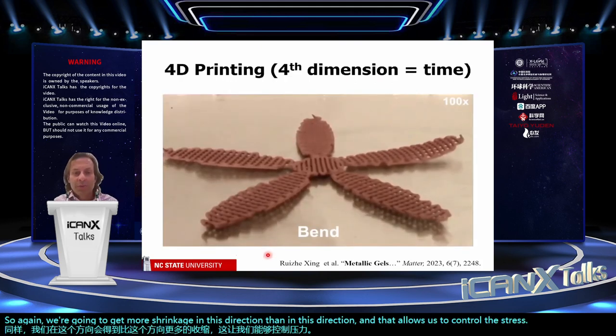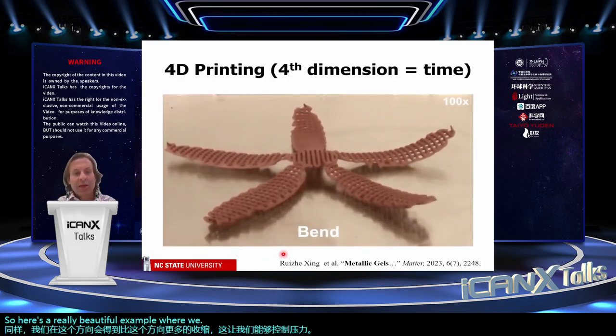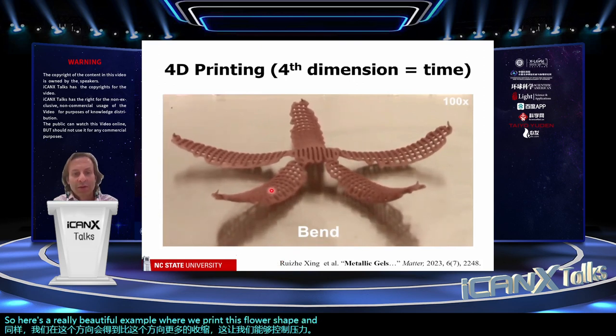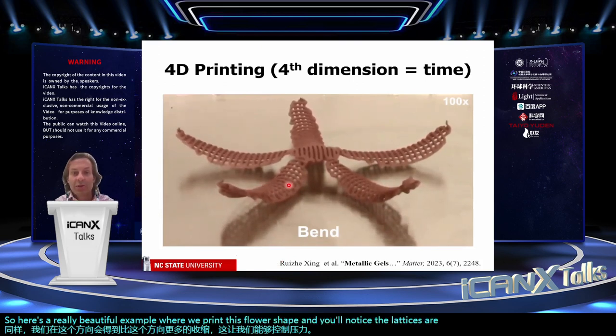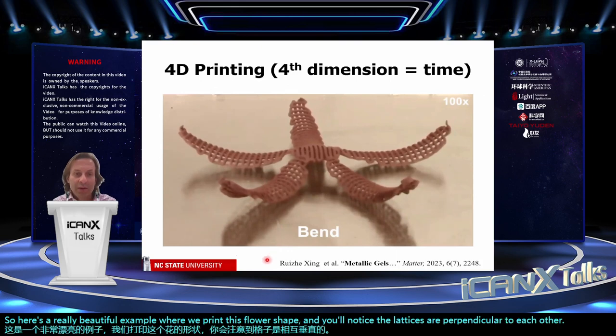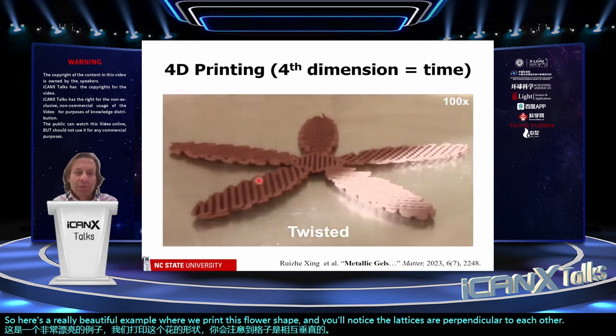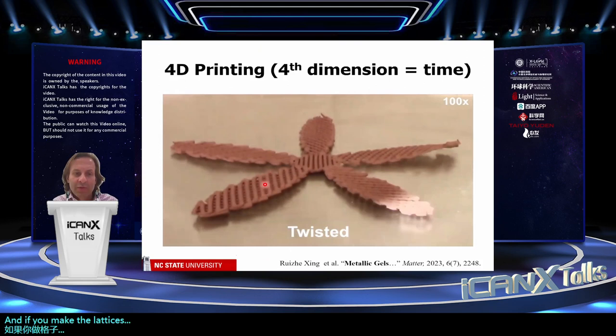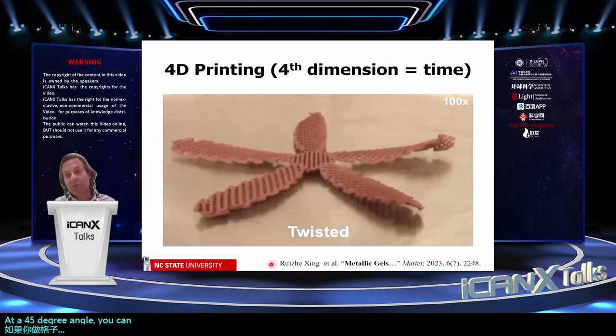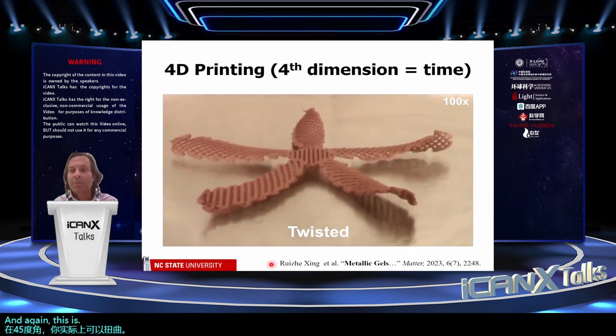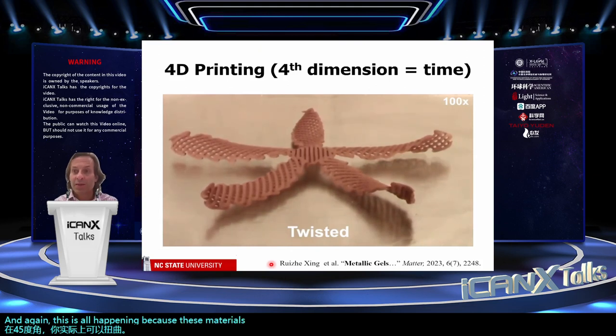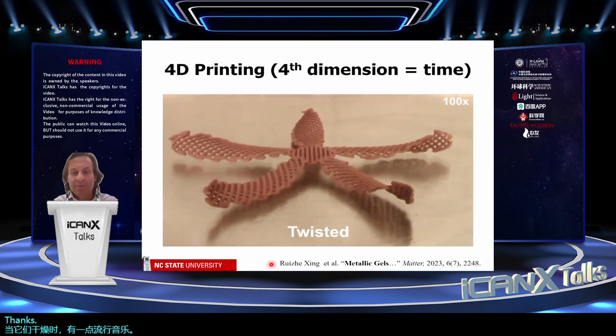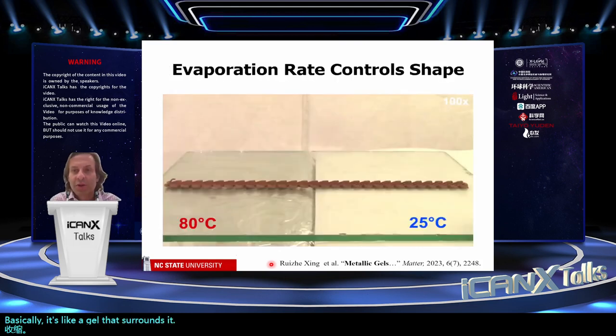So here's a really beautiful example where we print this flower shape. And you'll notice the lattices are perpendicular to each other. So we get bending. And if you make the lattices at a 45 degree angle, you can actually get twisting. And again, this is all happening because these materials are drying. And as they dry, there's a little bit of polymer that's put into these inks, and that causes the material to shrink. Basically, it's like a gel that surrounds it that exerts some stress.